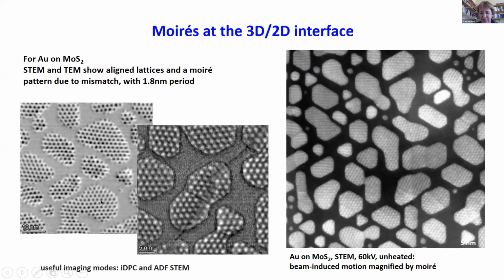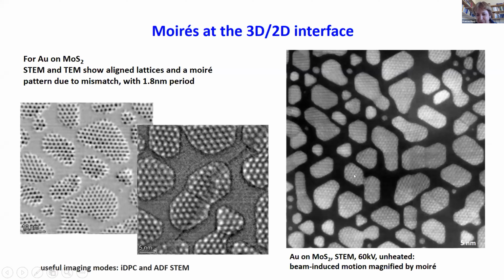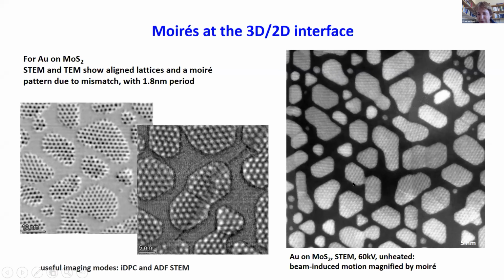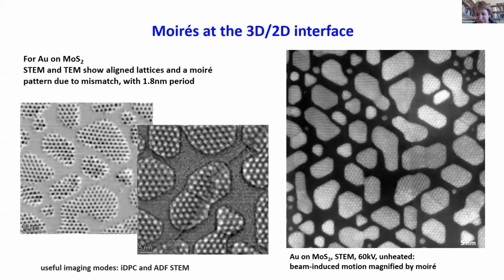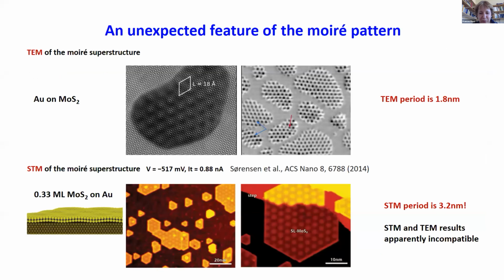So all of the lattices are aligned with each other, and the bonding is rather weak. You can see a little bit of jiggling just caused by the beam. The crystals are rotating very slightly, and the moiré pattern magnifies that rotation. Okay, so what can we do with this?